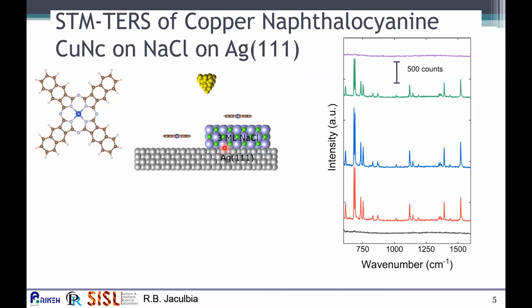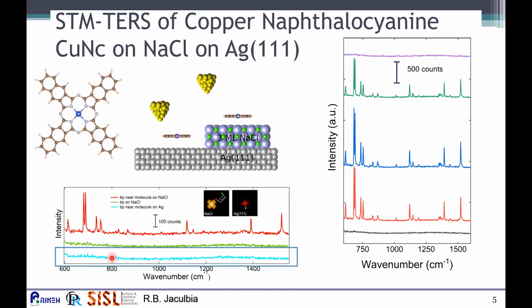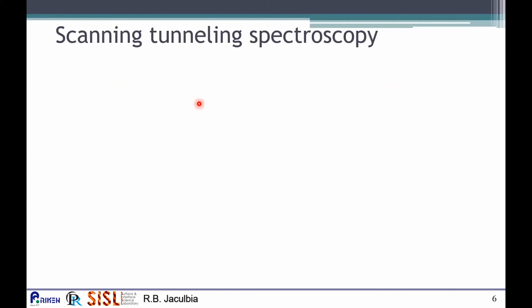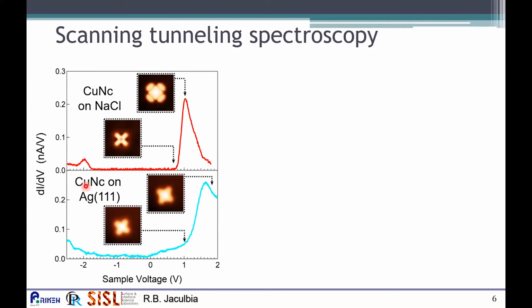More interestingly, when we place the tip near the molecule on the silver surface, no Raman signals were observed, whereas using the same tip under identical conditions, TERS signals are observable on the molecule on sodium chloride. In order to understand this, we studied the electronic structure of the molecule by using scanning tunneling spectroscopy. So we performed STS on the molecule on sodium chloride and on the molecule on silver 111. We observed clear, sharp peaks, both on the positive and negative side of the bias voltage for the molecule on sodium chloride, whereas very broad peaks were observed for the molecule on silver 111.